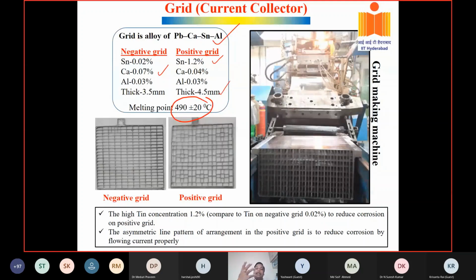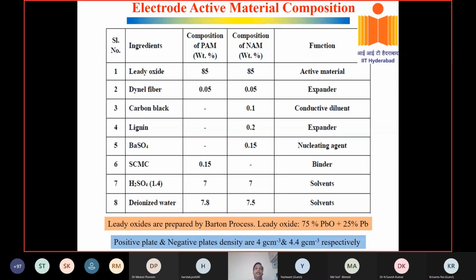So if you look at the active materials, we use leady oxide. Leady oxide is a mixture of Pb and PbO. It's about 85%. Denyl fiber is an expander because these are very hard materials. We use conducting carbon black, about 0.1%. Lignin is another expander. We use a nucleating agent, generally for the negative electrode, but for positive we don't use it. We also use SCMC, sodium carboxymethyl cellulose, a water-based binder,